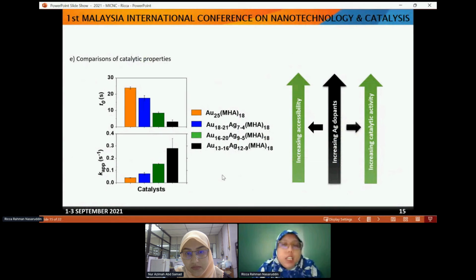Then we did the catalytic analysis. When we increase the silver dopants, it also increases the accessibility, even though we have similar types of ligands, and it also increases the catalytic activity. As you can see, when the induction time decreases, it means higher accessibility, because it takes a shorter time to start the catalytic activity. And when the apparent reaction rate constant increases, it means higher catalytic activity.